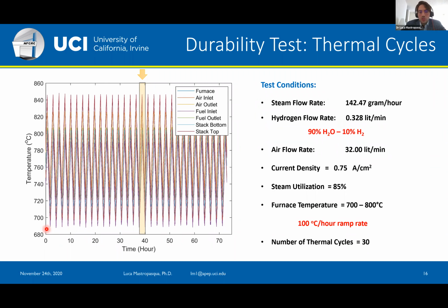varying the temperature of the furnace between 700 and 800 degrees C at a ramp rate of 100 degrees C per hour. And we performed 30 cycles. We didn't perform many. We didn't want to kill the stack right away. But the main idea was to understand whether this type of operating condition, varying the temperature of the stack, would degrade